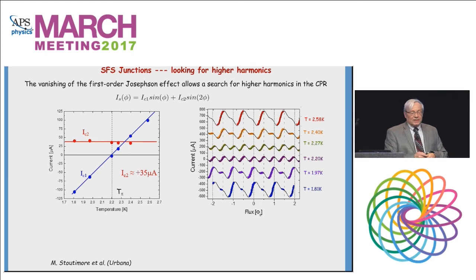So we looked at junctions, and when the critical current goes to 0, we notice that there is indeed a small sine 2 phi term. You can see it here. As the critical current goes to 0, it's periodic. Then it becomes doubly periodic, and then it goes back to being periodic again. So there is, in fact, a sine 2 phi term.